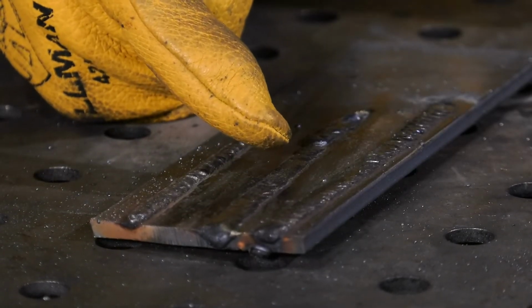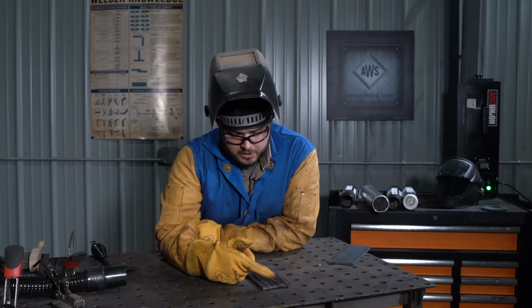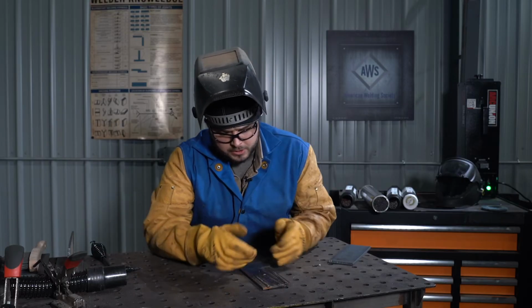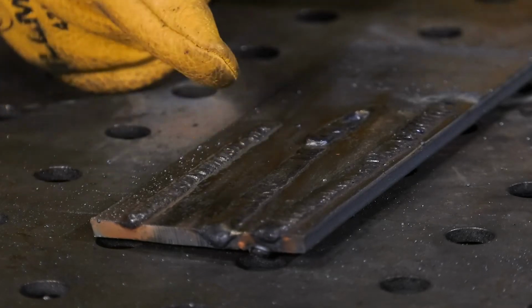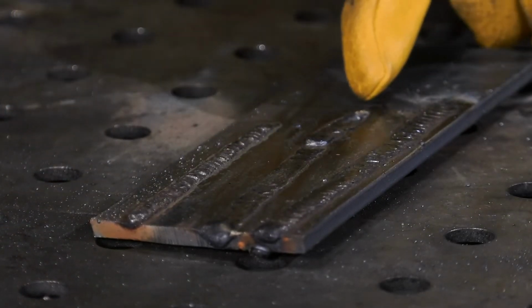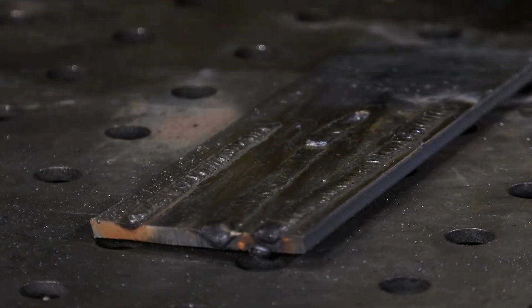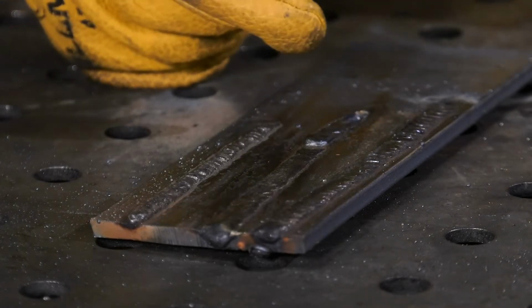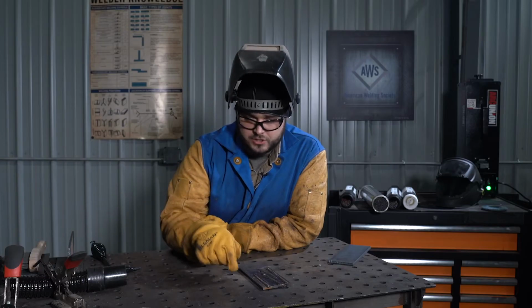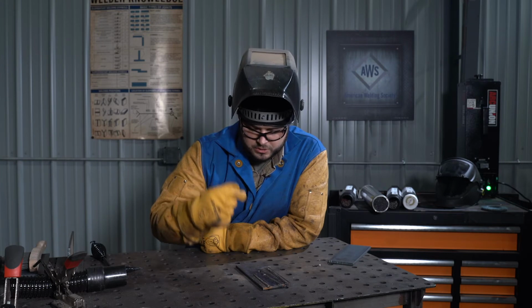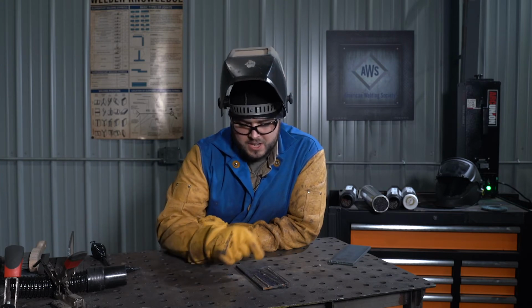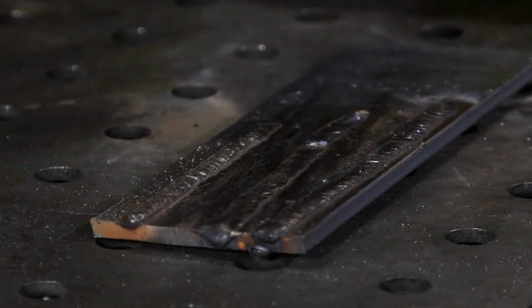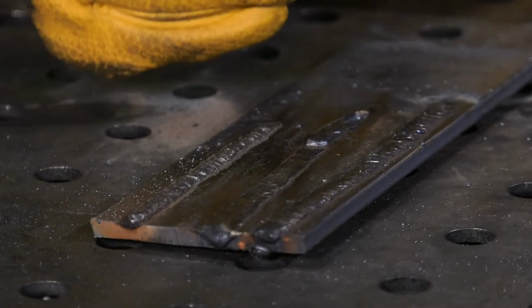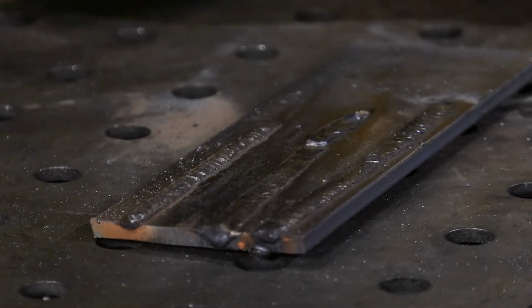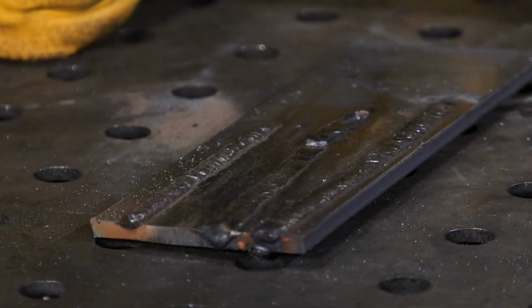Too much amperage or too high. Here, we have a very flat bead. You notice the ripples are very tapered as well. And we also see at the end of the weld where the crater is, it's very deep and dug in. While you're welding, you'll notice that the aggressive arc, because of the amperage, is really digging into the material, and you may have excessive spatter or smoke as it's burning too hot. Sometimes you may even see the electrode glowing if you have the amperage up high enough.